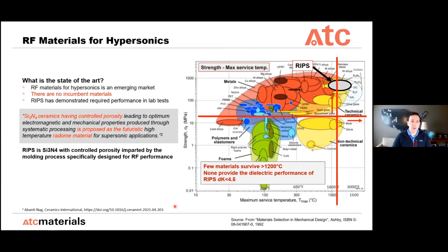So this chart here is a bit complicated, but the intent is that the y-axis here is material strength, x is maximum service temperature. So we need to be hotter than, let's say, 1200 degrees and greater than 150, 180 megapascals. So this top quadrant is really the materials you have to select from that'll just survive the flight environment. But now you also have to pick one that has dielectric properties that your antennas can see through and your sensors and seekers can receive and transmit through. So RIPS does exist up here, and this is a pretty small playing field of materials and market, which is why a small company like us can really find a spot for ourselves here.